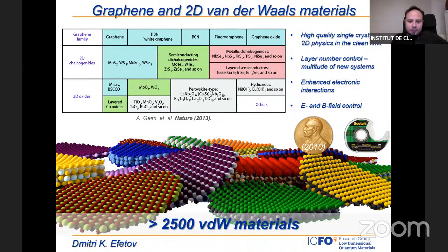The field really started in 2004 when Andre Geim and Kostya Novoselov realized that you can extract two-dimensional sheets of graphite from bulk graphite. This introduced the notion of graphene, which is just a two-dimensional plane of carbon atoms. These graphene layers were quite stunning because they were extremely high quality. You could study all the physics in the 2D limit, which was known from gallium arsenide, so you can study quantum Hall effect and things like that. Also, those layers were different if you have a single layer, bilayer, or trilayer system, so those are completely different electronic band structures. We could control the system with electric fields and magnetic fields very easily. So graphene was quite interesting.